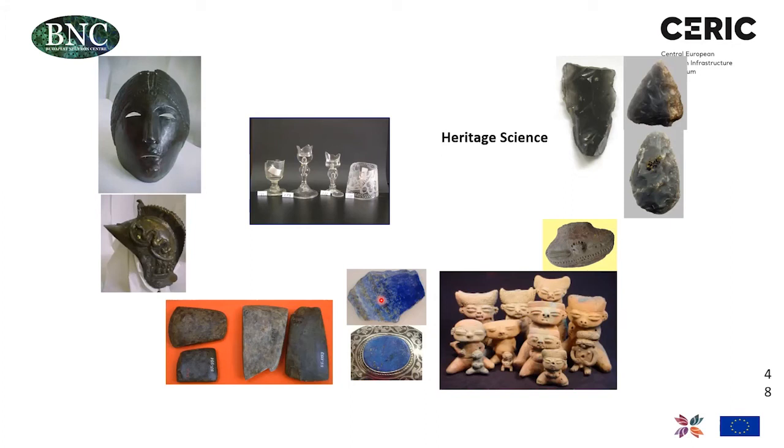Lapis lazuli was very widespreadly used blue paint in the Egyptian and medieval times, but only 5-6 mines are known where these are coming from, and fortunately they have different trace element patterns, so they can be nicely allocated to the mines. And this makes also possible to reveal the trading relationships between different people.